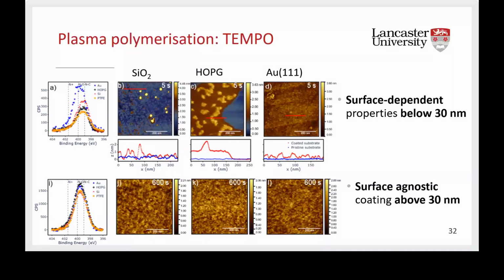And in figure A, there is the N1S spectrum. So we're looking at the bonding environment of the nitrogen atom of TEMPO, and you can see different environments depending on the surface. Then I deposited the polymer for a much longer time, 10 minutes, and now they are 30 nanometers thick, and you can see in figures J, K, and L some AFM scans. Now they all look the same, they have the same morphology. Then I checked them with XPS, and you can see in figure I that the N1S spectra, so the nitrogen bonding environments, are all the same. So the growth is actually surface agnostic.